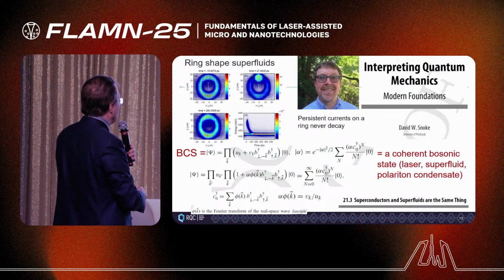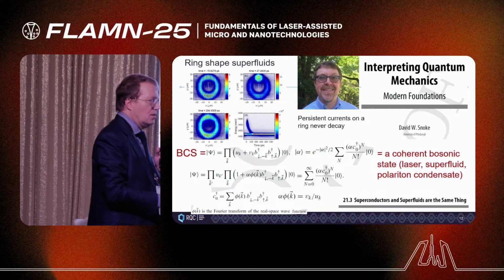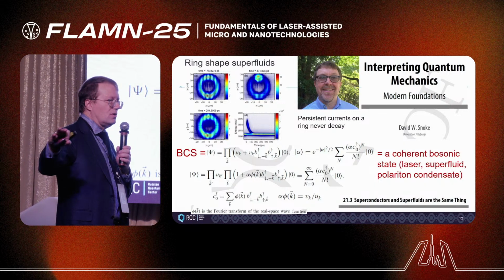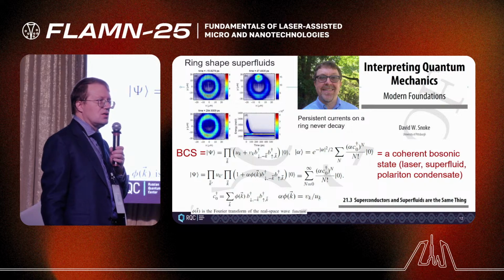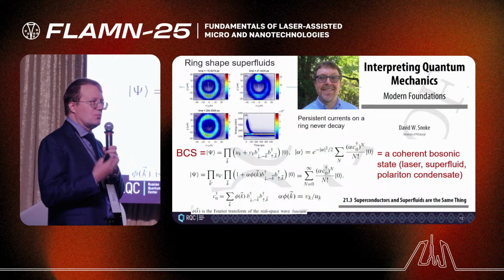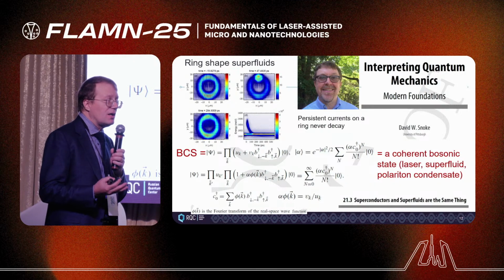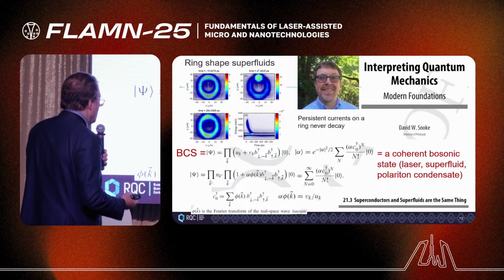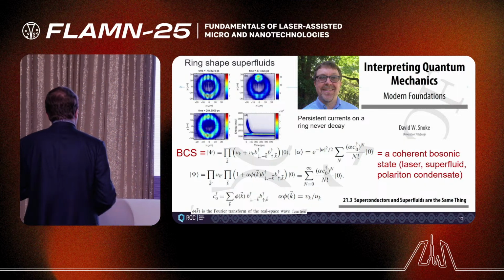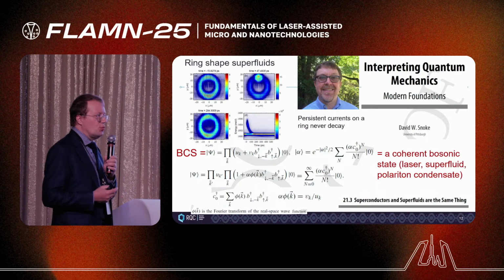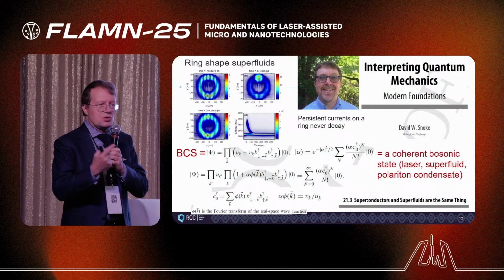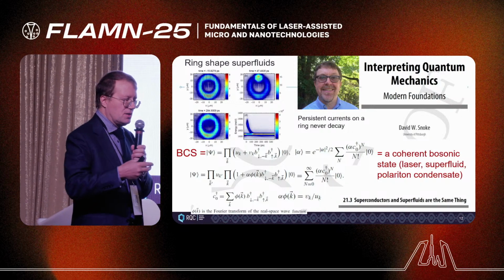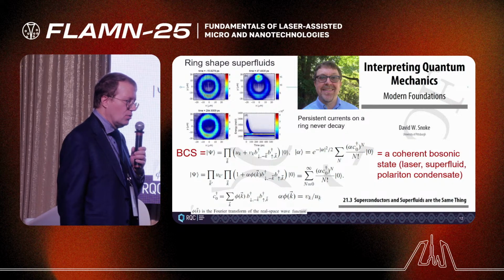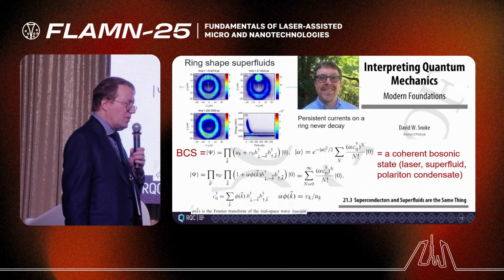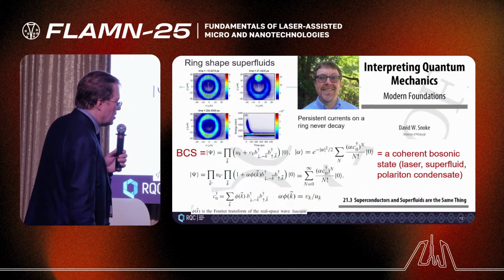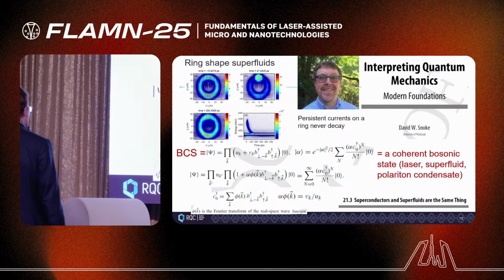That could be experimentally detected with optical interferometry. But the funny thing was that this motion was without any decay. So he kicked it once, and then for all the time he was measuring, there was no dissipation, no loss of speed. It was just moving, moving, and moving, like it should happen with a superfluid. No dissipation, no viscosity, just permanent motion. And it is also similar to what we observe in superconductors. Yes, in a superconducting circuit, if it is kept at a sufficiently low temperature, then for many, many years the current can circulate without any external voltage and without any losses.